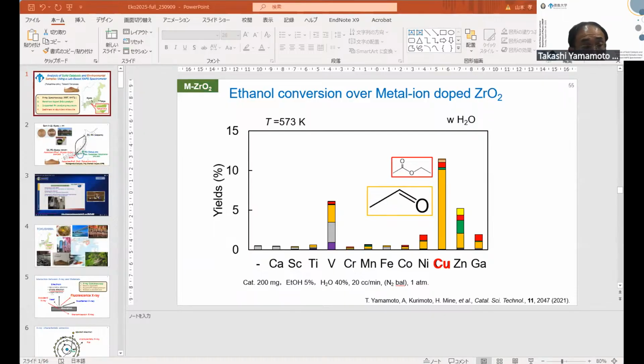Next, we first investigated the gallium ion, but then we changed the doped metals to 3D elements, the fourth period elements from calcium onward. You can see calcium, scandium and titanium have little influence on the catalytic activities. But vanadium, copper and zinc show different tendencies. Copper was found to be quite active for dehydrogenation, and the copper zirconia catalyst is quite active for ethanol dehydrogenation reactions.